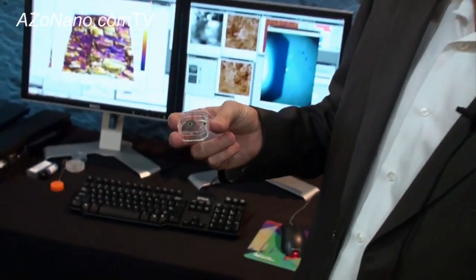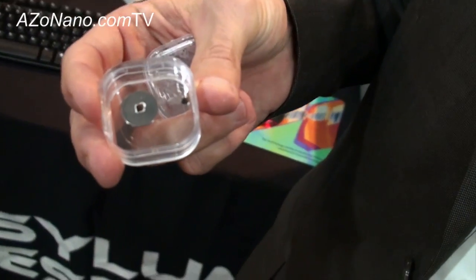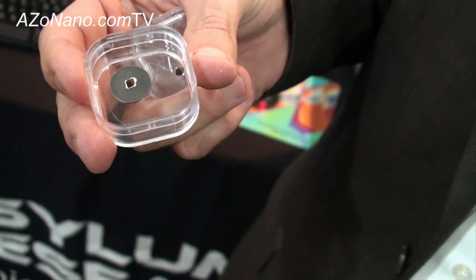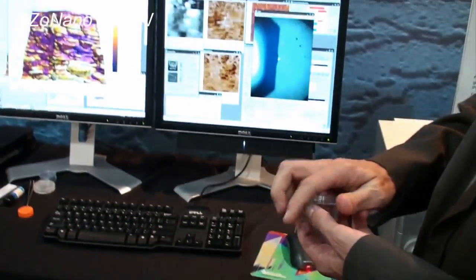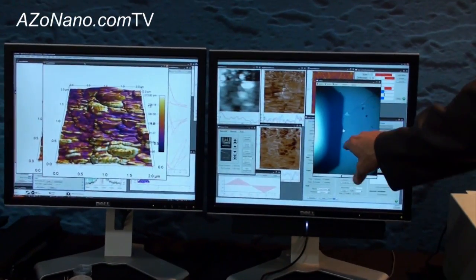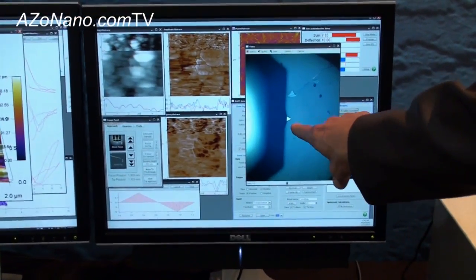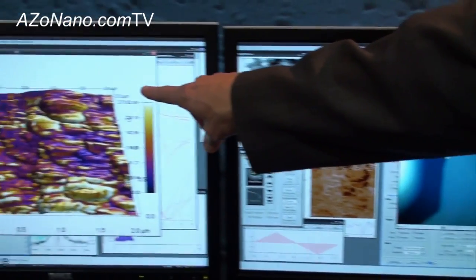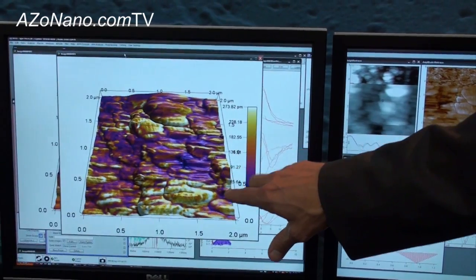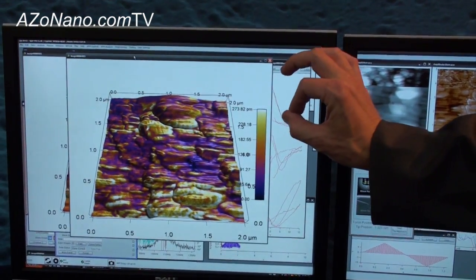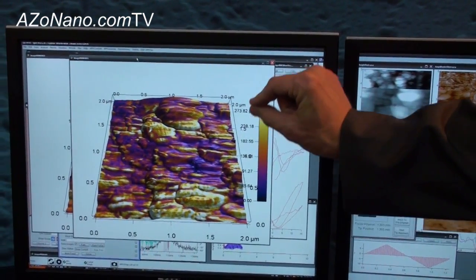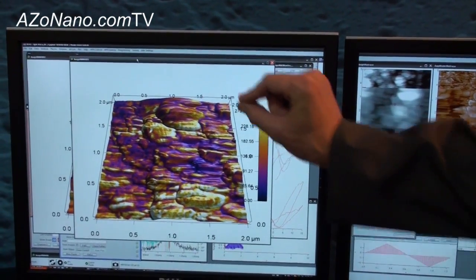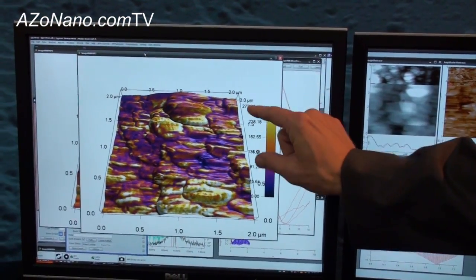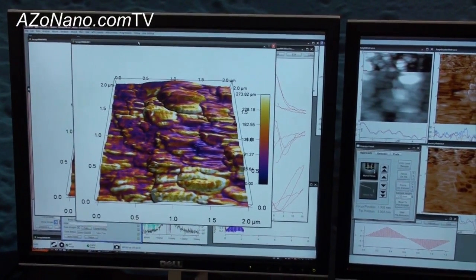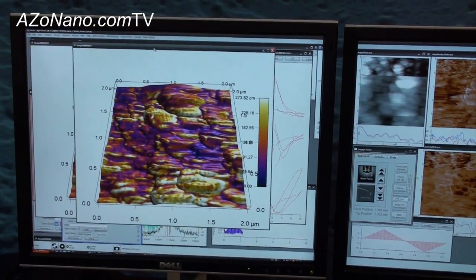Thanks a lot, Sergey. What we have here is a lithium cobaltate sample, much like the one that's in the microscope right now. This is a standard battery material. We've put that material in the microscope. You can see it here, and there's a small cantilever positioned above it. Now this image over here shows the topography of that sample, and the color here corresponds to the high frequency lithium dynamics, charging and uncharging as the lithium ions go in and out of that lattice. That's a high frequency measurement, probably made at about a megahertz or something like that.